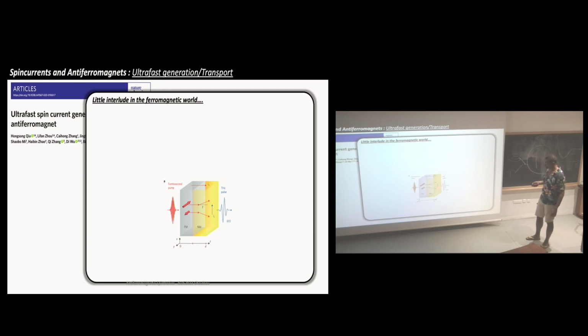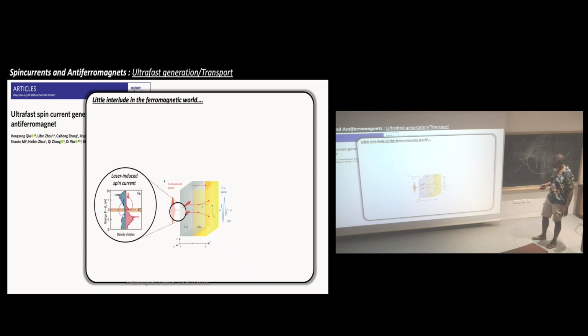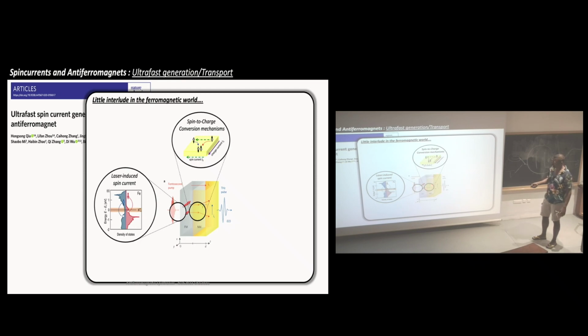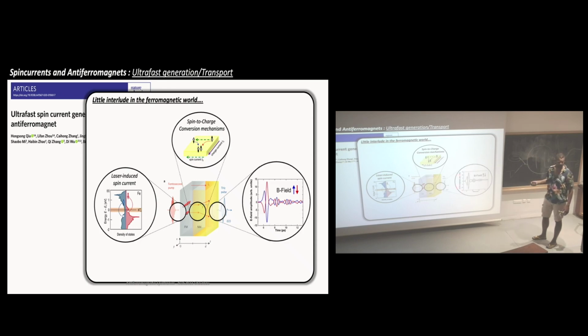So, little interlude. What's happening when you shine light, a femtosecond light, on ferromagnetic materials? Then you will generate an ultrafast spin current. I mean, it's a spin current, but on 100 femtoseconds time scales for different reasons, but one of them is that you have an unbalanced population of spin up and spin down. Then you generate the spin current. And this spin current actually can enter a normal metal, and if it's a heavy metal, will be charge converted. But this time, it will do this on a sub-picosecond time scale. And if it does that on a sub-picosecond time scale, then that will be the source of a terahertz field. Okay, so there is this whole activity, which is now called terahertz spintronics, because you can generate terahertz field with terahertz spin current, typically.